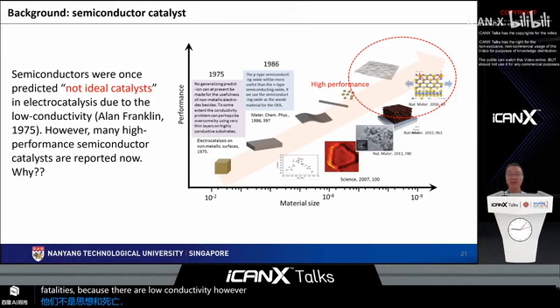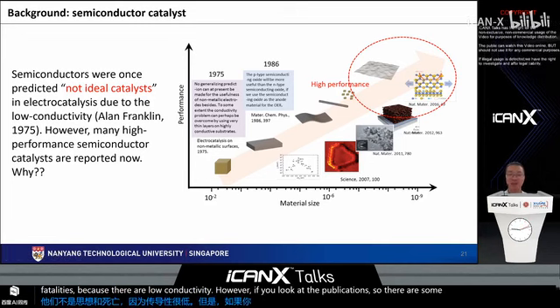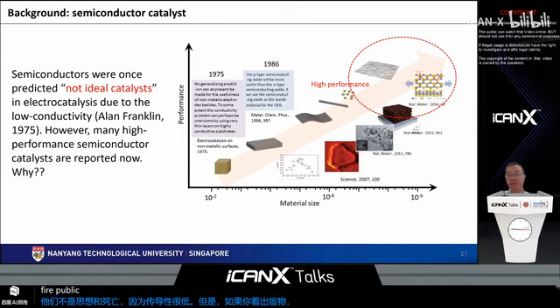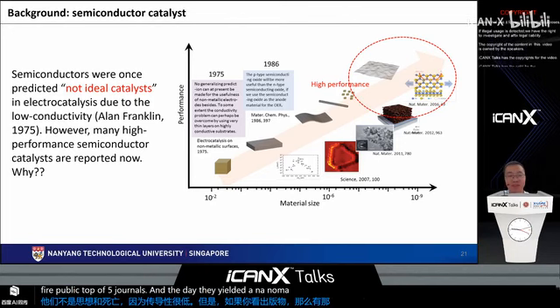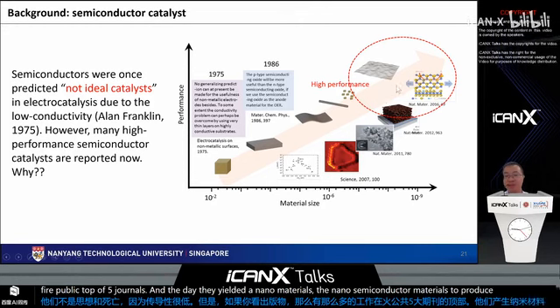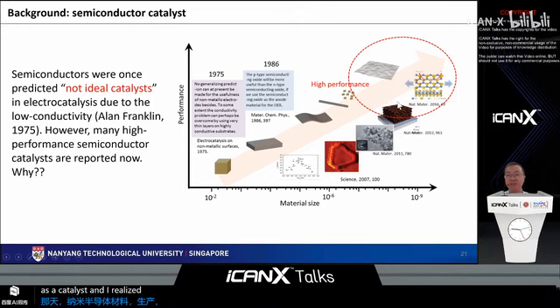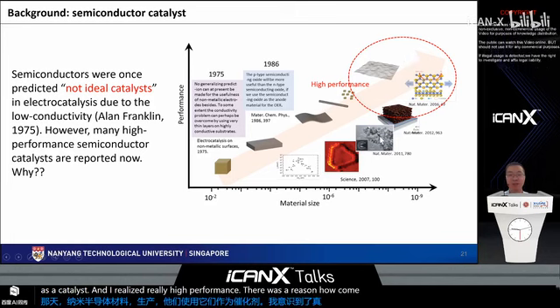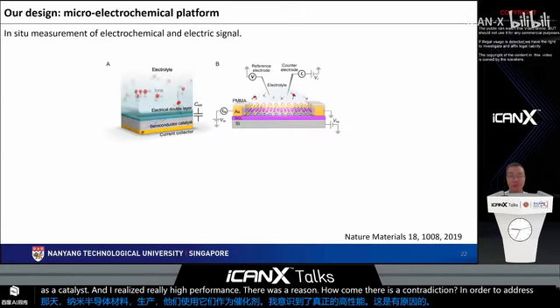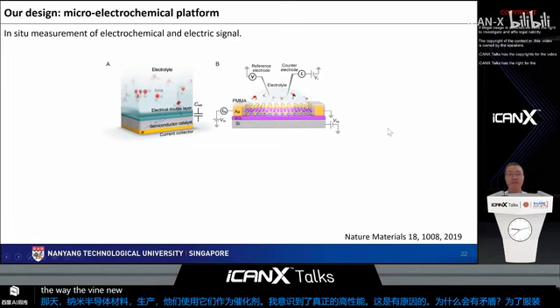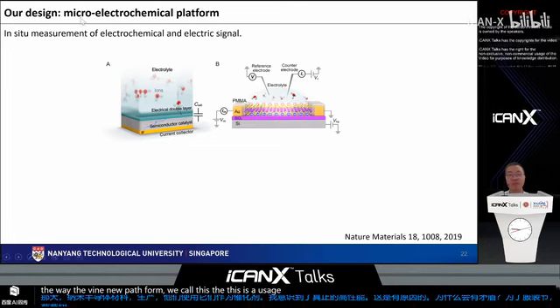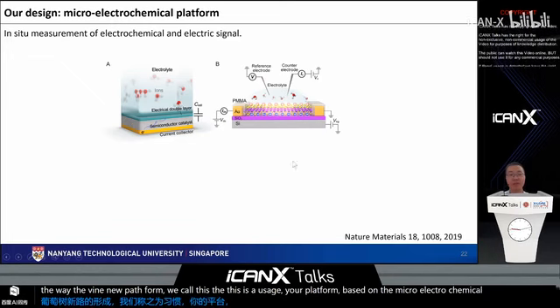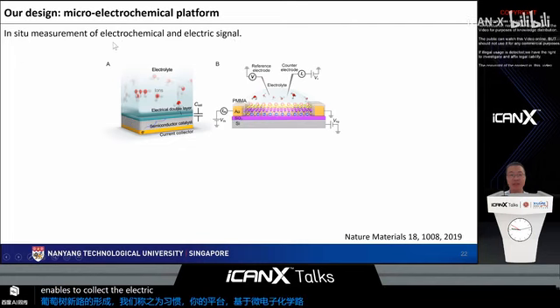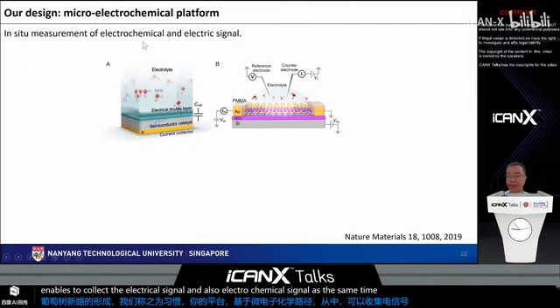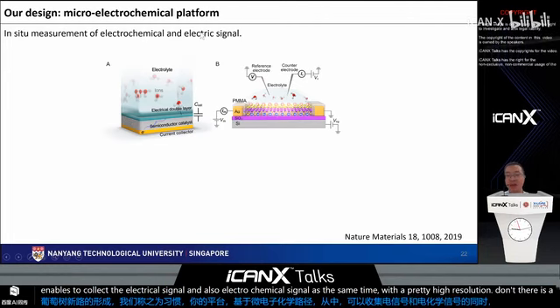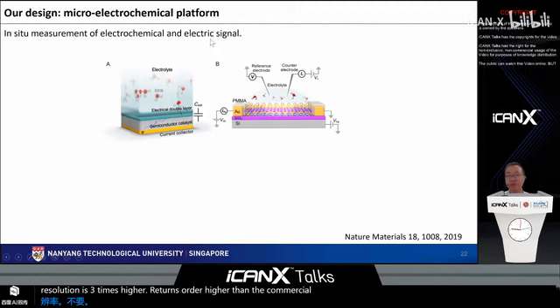However, if you look at the publications, there's so much work in top journals using nanomaterials, nano semiconductor materials, as catalysts and realizing really high performance. So what's the reason? How come there's a contradiction? In order to address this, we designed a new platform. This is an in situ platform based on a micro electrochemical platform, which enables us to collect the electric signal and also the electrochemical signal at the same time with pretty high resolution. The resolution is 3 orders of magnitude higher than commercial equipment.